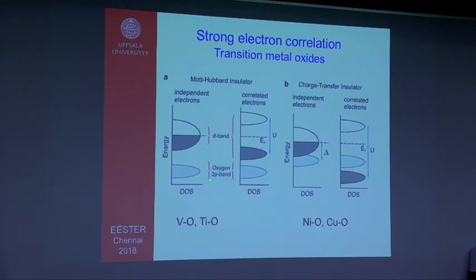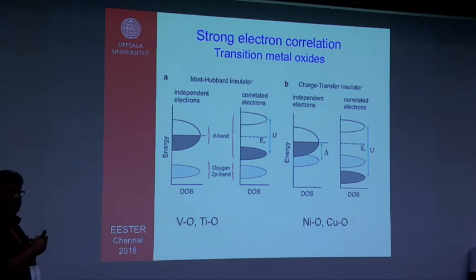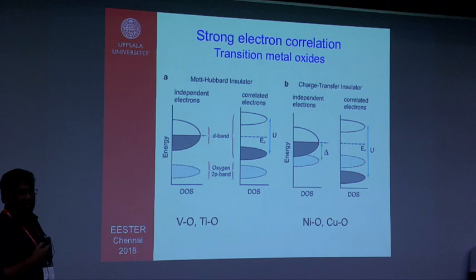So a poor man's view would be to actually add an extra Coulomb interaction with it in the form of this U, and what you do here, you split this band, metallic band, into two parts. You split by an energy value U, which is the value of the Coulomb repulsion, and what you have here, you have this sub-band which is filled, and you have this sub-band which is empty. So these are called the lower Hubbard band, and this is the upper Hubbard band, according to John Hubbard's formalism, which is separated by a Coulomb repulsion unit. This is actually the correct picture. Here the gap opening is not coming from anything else, but it's coming from the strong electron correlation, which is absent in our normal standard approximations.